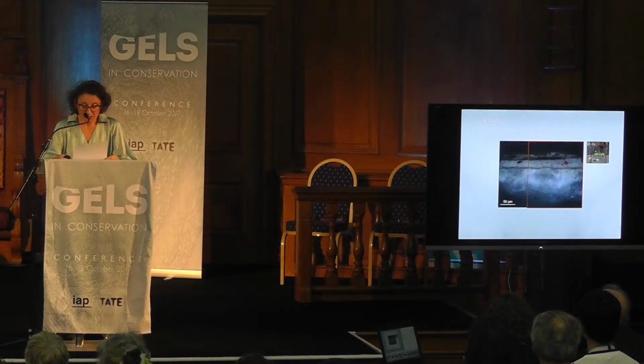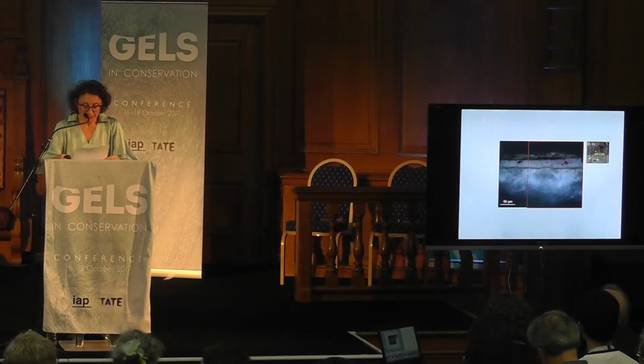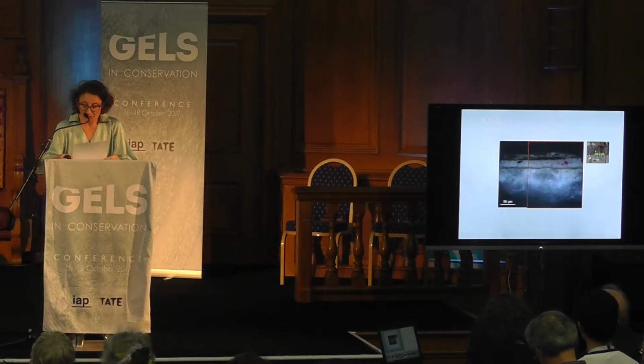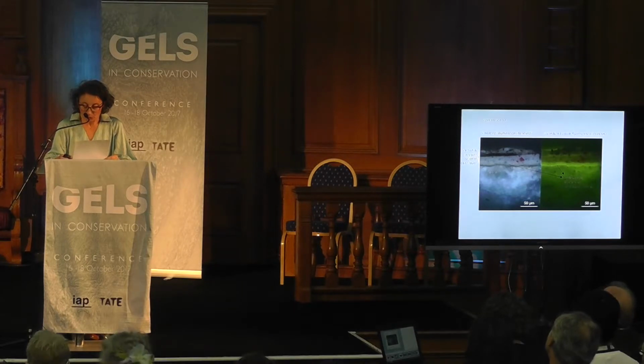The impact of the wax consolidation treatment on the paint layer structure is illustrated in cross sections removed from areas without blisters. Cross section 12 was prepared from the foreground, and the relatively simple original layer structure was consistent with the stratigraphy observed in other areas. The gypsum base ground layer was followed by a medium-rich preparatory layer, which appears white or translucent in visible dark field illumination, and which has strong outer fluorescence under ultraviolet illumination. This imprimatura layer consists of a mixture of lead white and a drying oil.